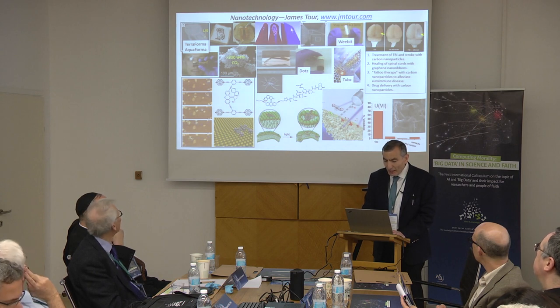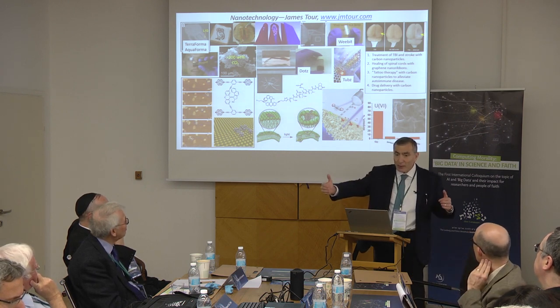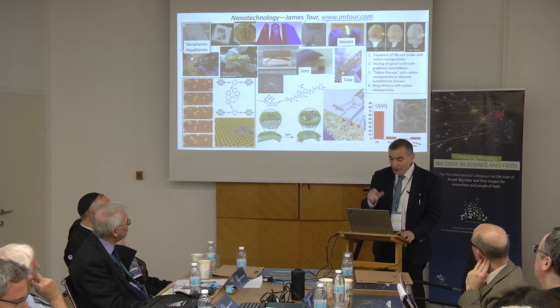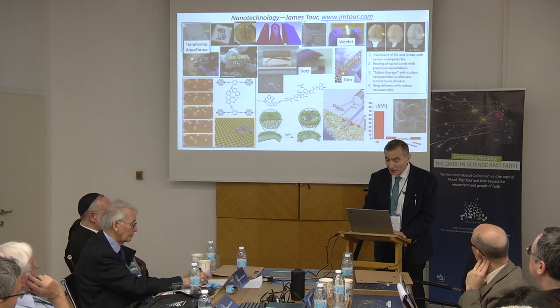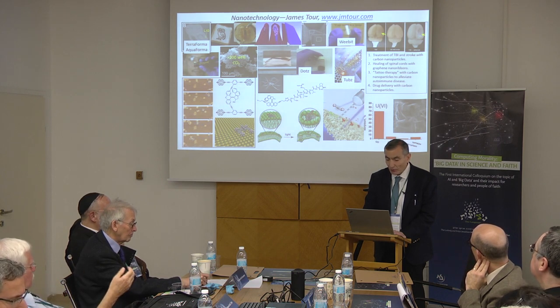This is an area where we've learned how to make graphene nanoribbons. We just split multi-walled carbon nanotubes into graphene nanoribbons — about 250 microns long, about 100 nanometers wide, and 1 nanometer thick. This is a commercialized process. You can buy these from Sigma Aldrich, now Millipore Sigma, because it was licensed by EMD Merck, which owns Sigma Aldrich.